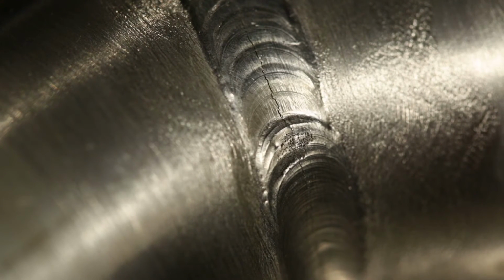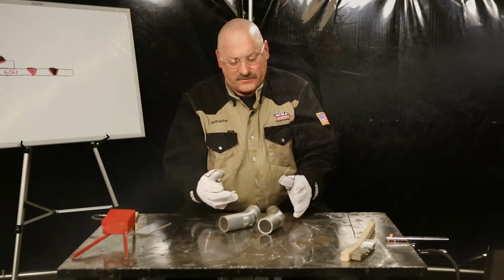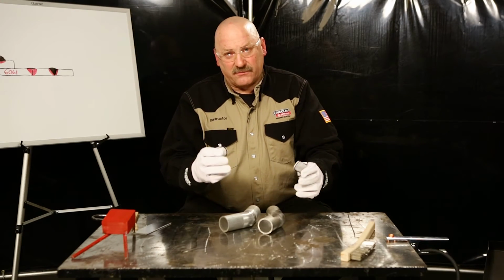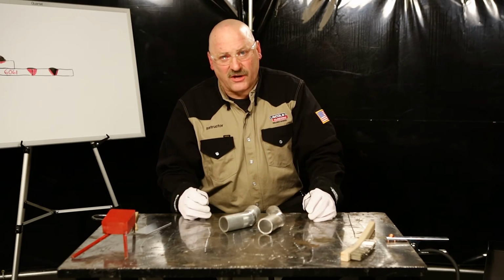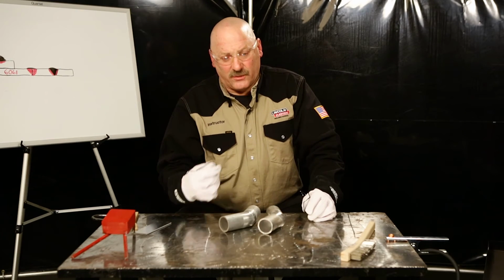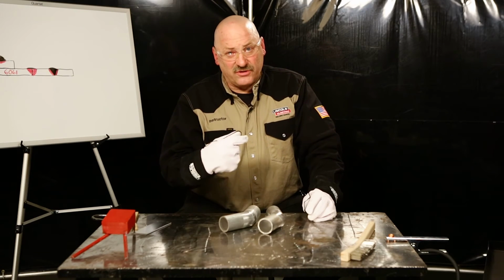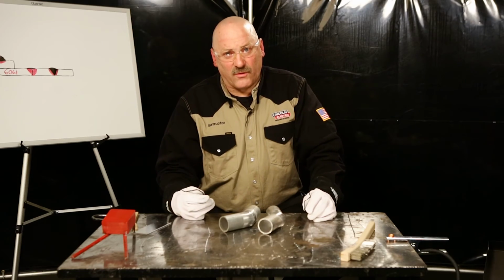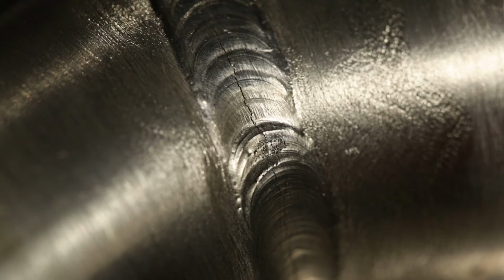Sometimes you'll see that if you look at hand railing at amusement parks and things like that made out of aluminum, where they miter cut and weld afterwards. Sometimes they sand those welds off, and you'll see right where the weld used to be, and there'll be a small hairline crack. And that's usually the result of not beveling that aluminum before you weld on it, or opening it up so you can get plenty of filler metal in there.